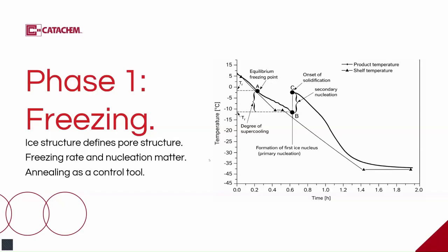When making freeze-dried beads or lyo beads, the reagent droplets are flash frozen in nitrogen, so control of freezing here is impossible. However, other formulation variables are required to maintain the integrity of the lyo bead. These beads, for those not familiar with them, are tiny freeze-dried spheres of product, 10 to 20 microliters in volume, that freeze dry as spherical nuggets. We will talk more about these a little later on.